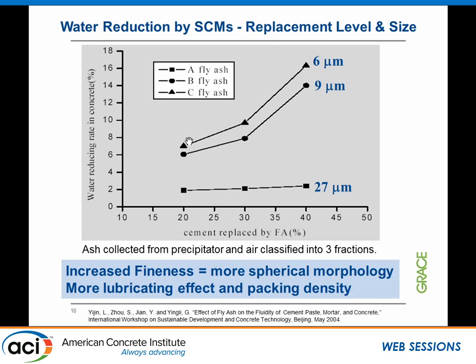And then some other things that we are looking at when we are dealing with fly ash. In this example, the group really looked at a fly ash divided into 3 different particle sizes, a coarser fly ash and a finer fly ash content. You can look at this in here. This is the water replacement rate, 18% on top, and fly ash level replacement rate. The coarse fly ash in here really did not give us too much water reduction level.